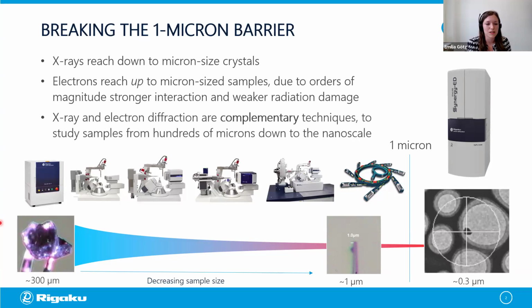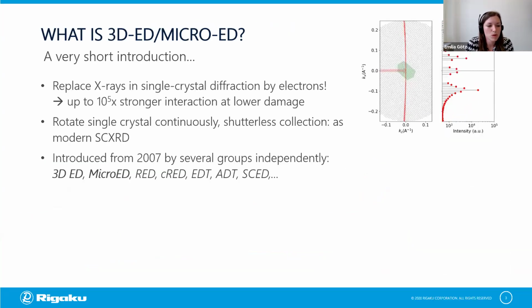Of course, if the crystals get bigger, then electrons will just not pass through, such that electron and X-ray diffraction are actually complementary techniques to give you access to a whole range of crystal sizes from the nanometric regime all the way up to millimeter-sized crystals. In most modern electron diffraction techniques, the measurement scheme is very similar to single crystal X-ray diffraction, where you basically replace X-rays by an electron beam. So you have a crystal which rotates continuously in the beam, and you do a shutterless continuous collection.